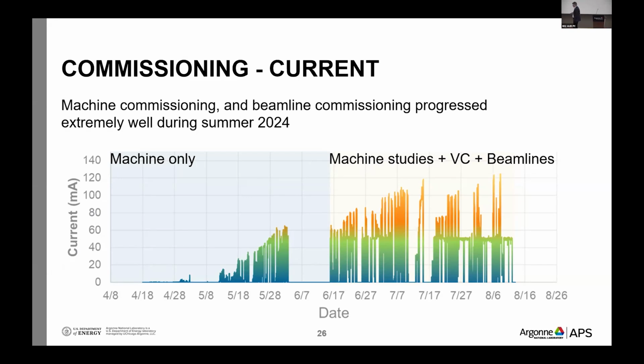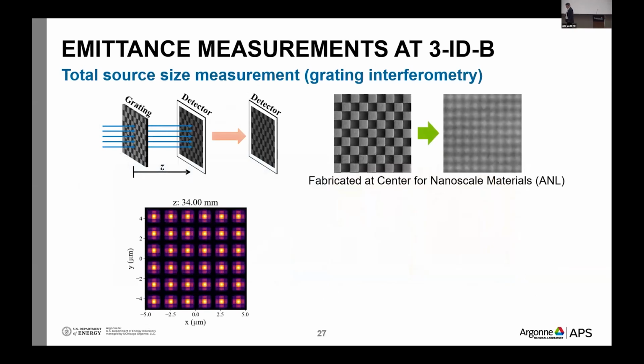And then in the summer, we divided our time in different periods. So during the day, we would do beamline commissioning with a current of about 50 milliamp. And then during the night, progressively, we would ramp up the current. The purpose of that was that the electron beam and the X-rays generated by the electron beam actually help improve the vacuum. It's essentially scraping off all the residual molecules in the vacuum system. So we had this mixed period where we were doing beamline commissioning during the day and vacuum conditioning at night. It was pretty successful and we quickly ramped the current above the current of the old machine, and eventually went all the way to 200 milliamp more recently.